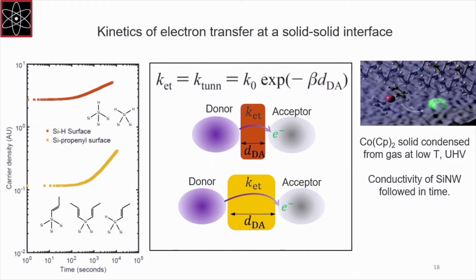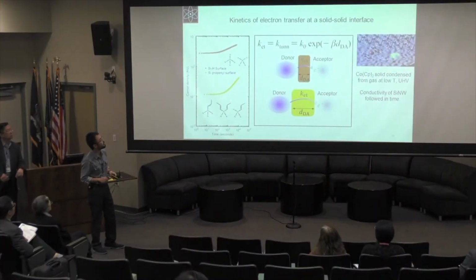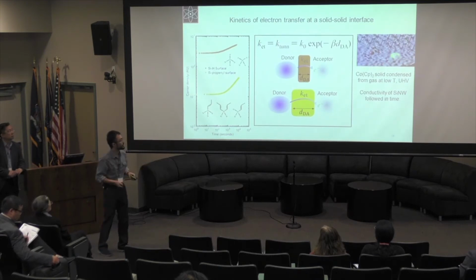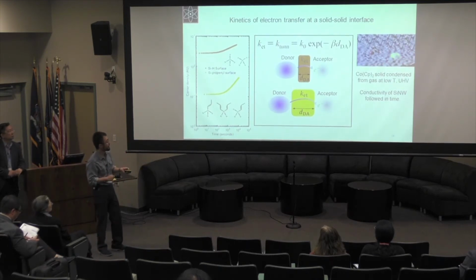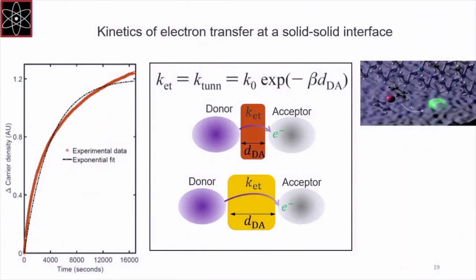And the structures are like mixtures of different geometries, because you can never get a homogeneous chemical structure on something with the extent of surface roughness that we see on those nanowires. But the qualitative trend is quite clear in that by increasing the separation between the two, the rate and also the extent of reaction of this process goes down dramatically as you increase the spacing. So we wanted to get some more quantitative understanding of these curves. As any scientist would do, after getting data like that, we try to impose an exponential fit. But obviously, there's some deviations.